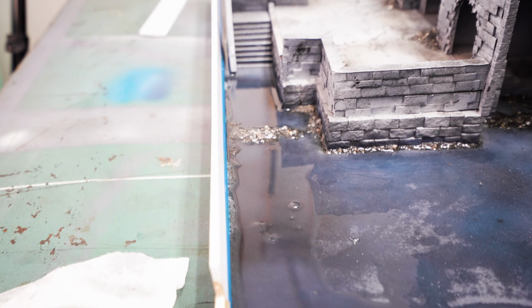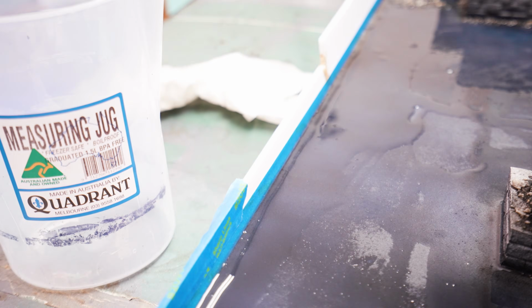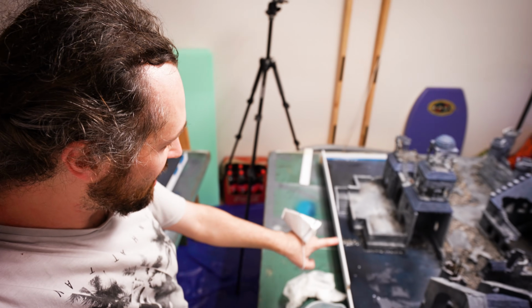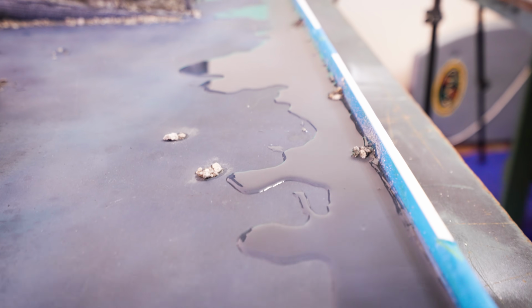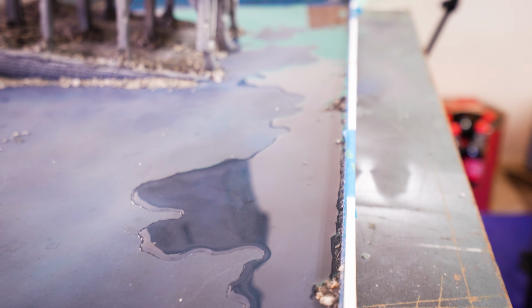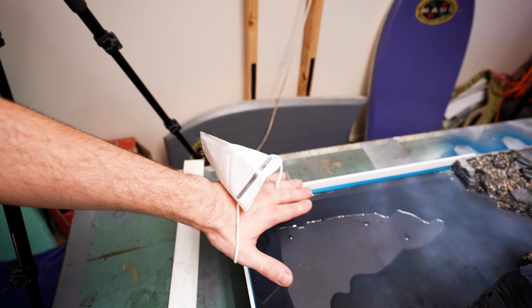So that is our baby pour done, and it's been about 10 minutes and there's no leak. So that means we've got no kind of catastrophic problems, no big holes that are being immediately exposed by the resin. Now I think what I'm gonna do is leave this about half an hour to an hour and just see if there's any tiny micro cracks that are gonna be a leak. If there's not, then we'll complete this layer so that it's one consistent skin of resin, very, very thin, only a couple of millimeters. So that way, as it starts to dry, there's no weird tidal marks through. That'll be another test of those joins.